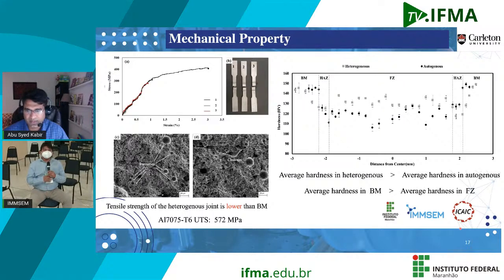And if we see the average fusion zone hardness, we found that the heterogeneous hardness is more or less higher compared to the autogenous weld. So the equiaxed microstructure was even stronger than the dendritic microstructure.